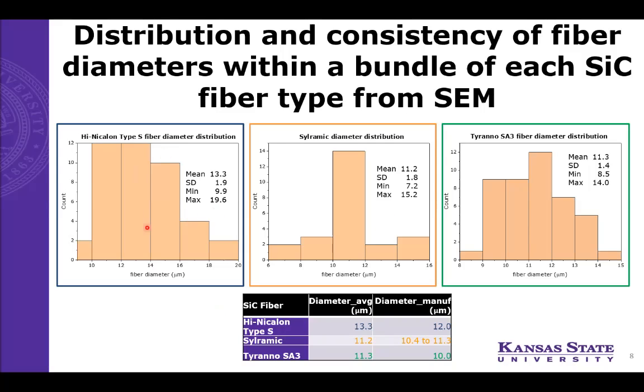where we have a general distribution for this Hi-Nicalon type S fibers with an average diameter of 13.3 microns, as well as on the Sylramic, we have a general average of 11.2 microns, and the Tyranno SA3, 11.3 microns for their diameter. And we can see how this compares to the manufacturer's data by looking here. Our Hi-Nicalon type S average and our Tyranno SA3 average are actually 1.3 microns above what the manufacturer suggests is their fiber diameter. However, the Sylramic fits right in the range provided by ceramics manufacturers. So that's kind of nice.